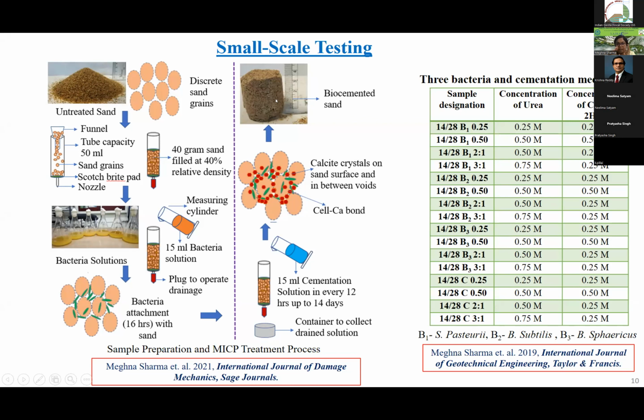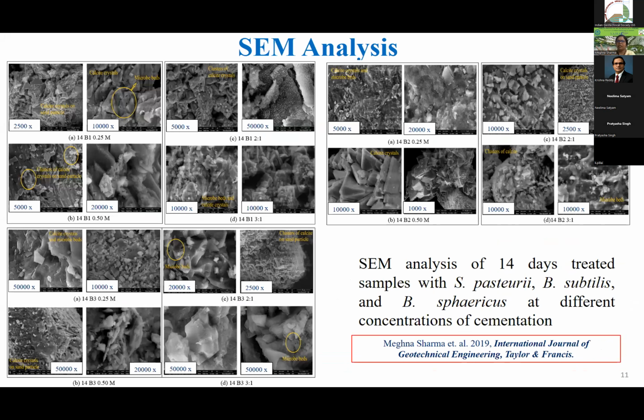Okay, as visibility also we can analyze, the sand particles got bound. Okay, so scanning electron microscopy was carried out, and through this method especially, one thing is very interesting: we can see the microbe bed also, where the microbe was present, so it can show microbe-attached calcite precipitation. Okay, and in all figures you can see there is presence of calcite crystal.